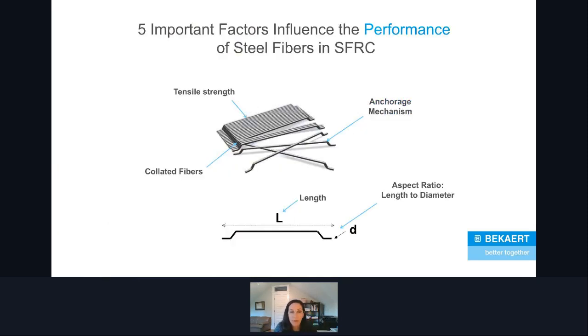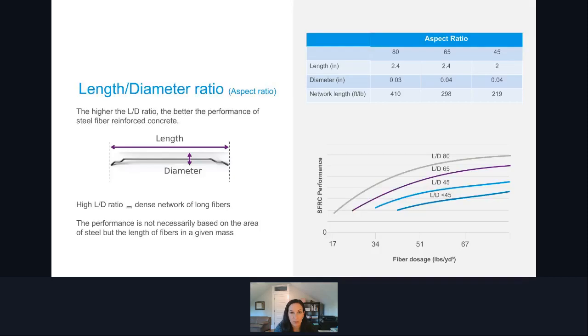So we have identified 5 factors which influence the performance of an SFRC. And these 5 factors are specific to the steel fibers themselves. Now, of course, we can't ignore the impact of the concrete that the fibers are within, but for the purpose of today's conversation, we'll focus only on the steel fibers themselves. So these 5 factors are the tensile strength, the anchorage mechanism, the aspect ratio, which is the length divided by the diameter, the length itself, and the collation or the distribution method of the fibers. And we'll go through each of these in a little bit of detail.